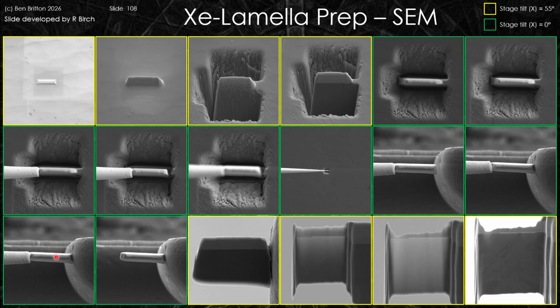We can then, once it's been nicely welded, we can cut it free, and then this is the sample as stuck on here. At this point we might want to put some more deposition just to secure it a bit more. And then we can effectively polish to give us the electron transparent window. Here we can basically also have reinforcement, so we see that we haven't thinned it fully, and that can be useful to try and reduce the influence of residual stress and bending in the thin lamella that's formed. And you can see this is the 10 kV and then this is the 5 kV imaging that's presented here.